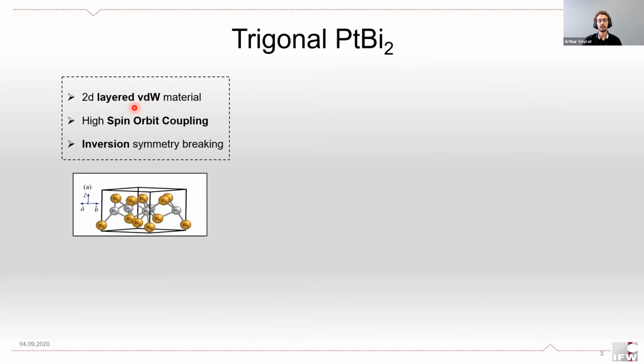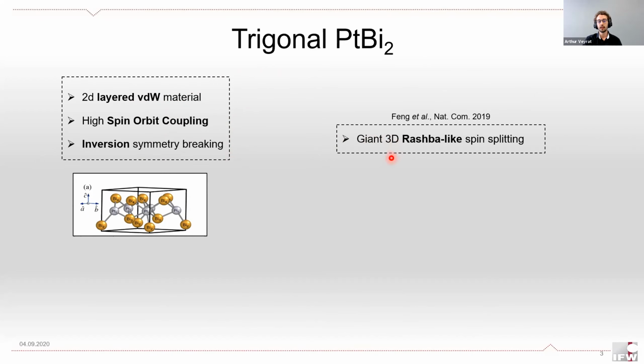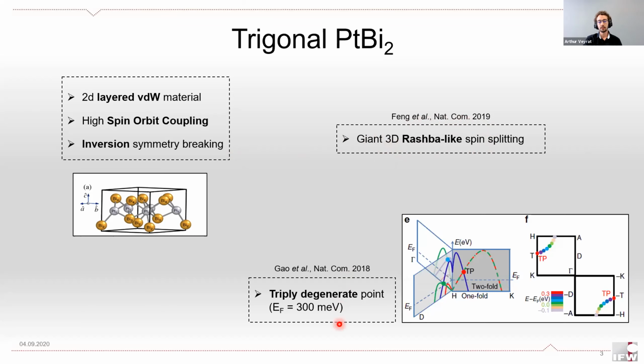As I said, it is a van der Waals layered material. Each layer is made of 2 inequivalent planes of bismuth with 1 plane of platinum in the middle. So the compound shows a high spin-orbit coupling as well as an inversion symmetry breaking. These last 2 points give rise to a giant 3-dimensional Rashba-like spin splitting, as has been recently observed. And some theoretical calculations have shown the existence of a triply degenerate point in the band structure at about 300 meV above the Fermi energy.